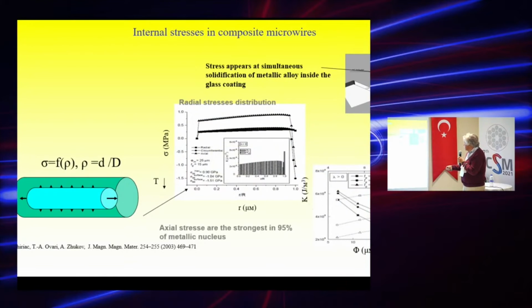So the most important ones are the axial ones. This is the radius of the inner metallic nucleus, so the interface between glass and metal, and the strength of these internal stresses increases with the thickness of the glass. Of course, it's obvious because if the glass is thicker, the internal stresses are larger.